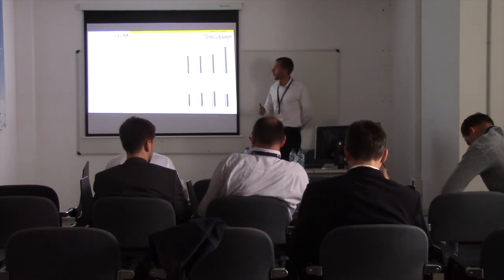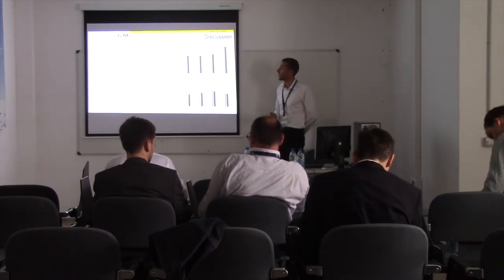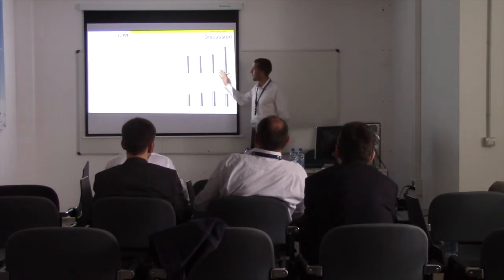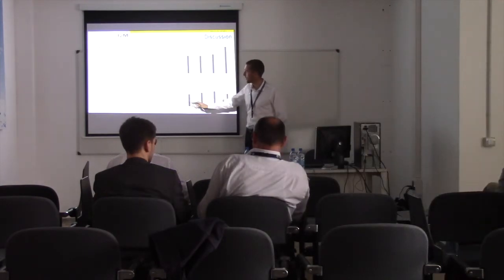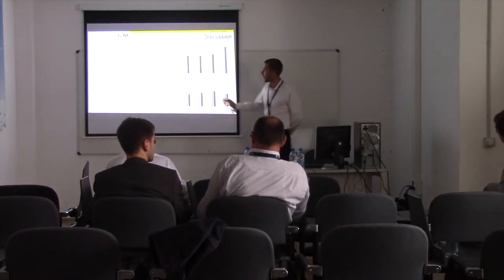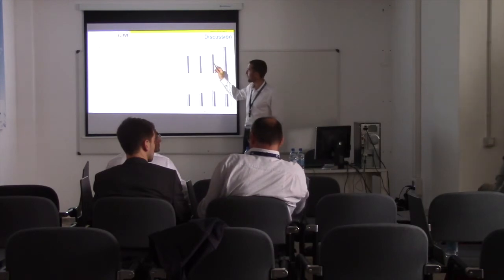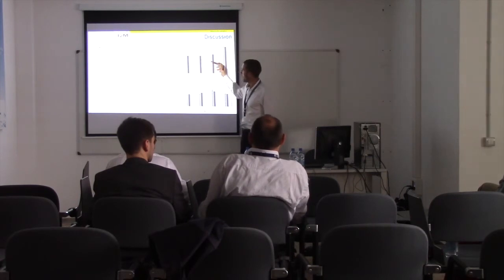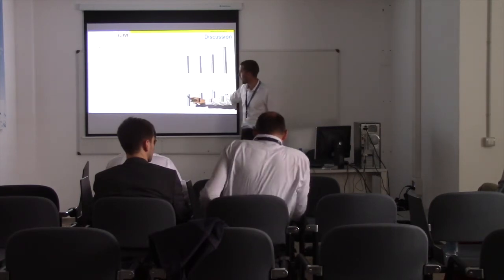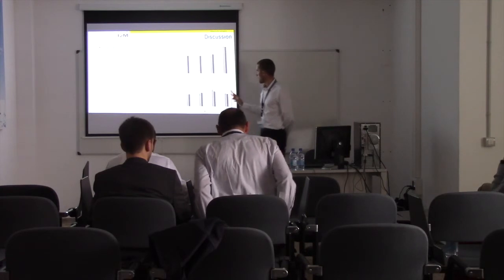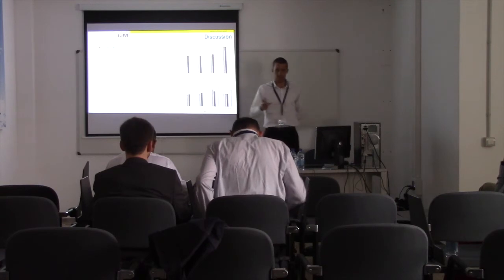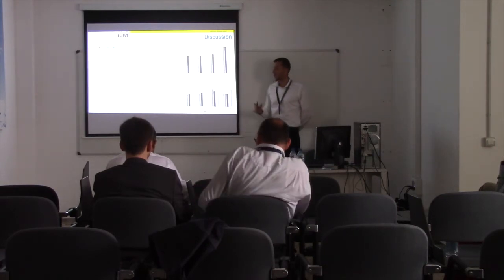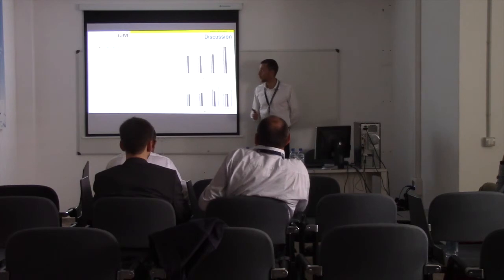From this work, we tried to check experimentally. So here you have some results for different powder bed thicknesses for apparent density and apparent surface. You can observe that for the thinnest thickness we have a drop of the packing density, and also a drop for the apparent surface, which suggests that our simulation gives us a qualitatively good point of view.